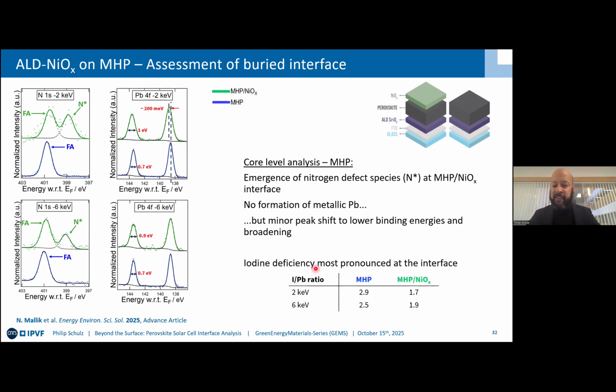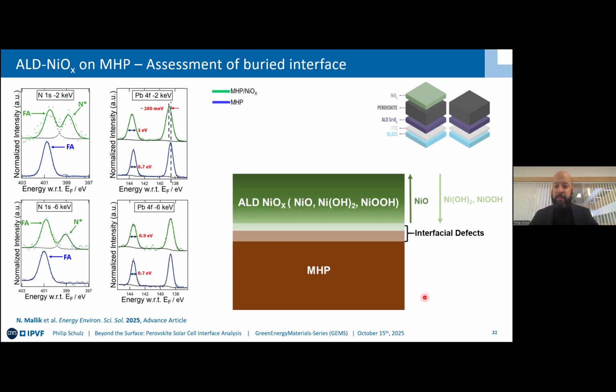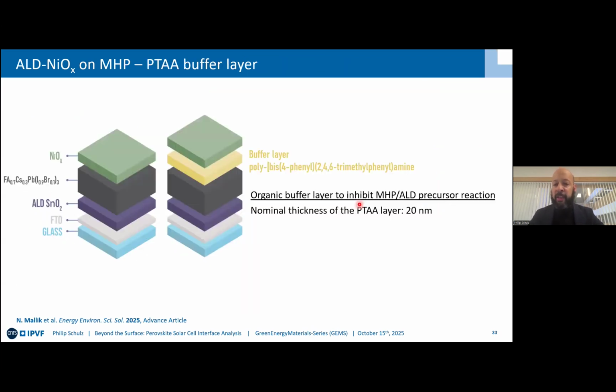As it comes to the iodine deficiency, it is there again. So we get iodine deficient interfaces, though the case is less aggravated than it was before for the tin oxide precursor. So here we actually make a very quick summary. Yes, we get these interfacial defects, but what is actually more telling is the gradation in the nickel oxide that is on top of the perovskite, and that should be really detrimental for hole extraction. And so then we actually buffer this in order to make the nickel oxide grow a bit more conformal and according to our wishes and our goals.